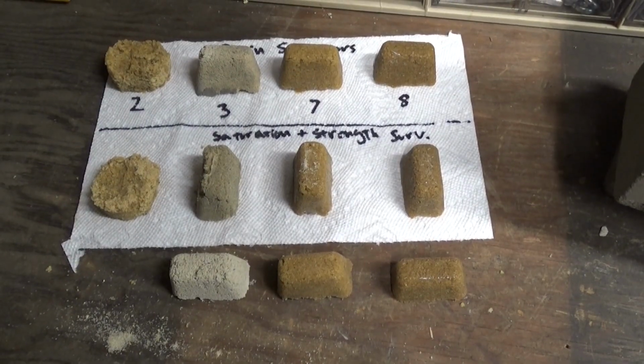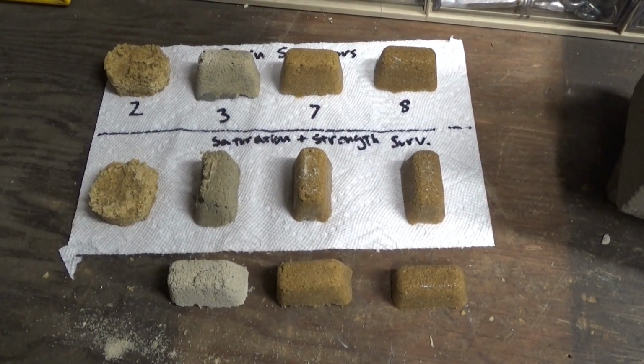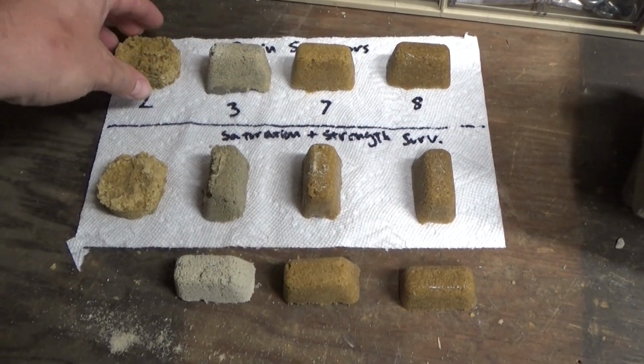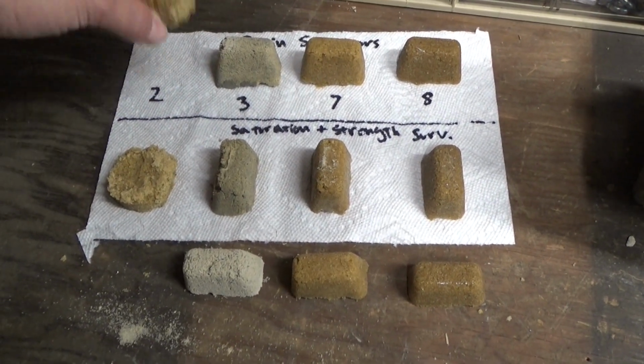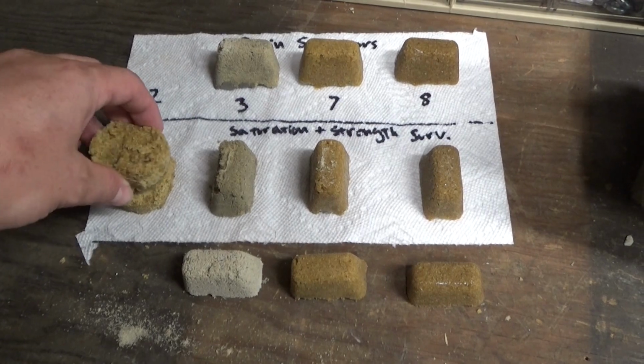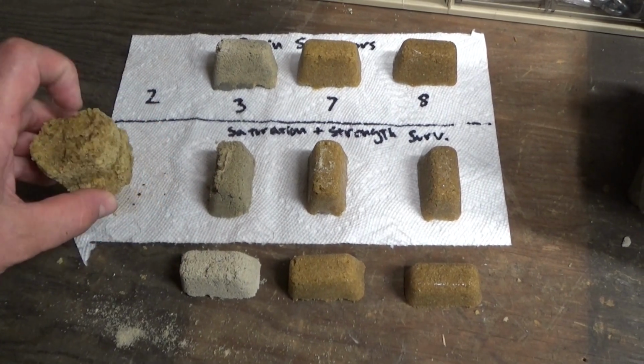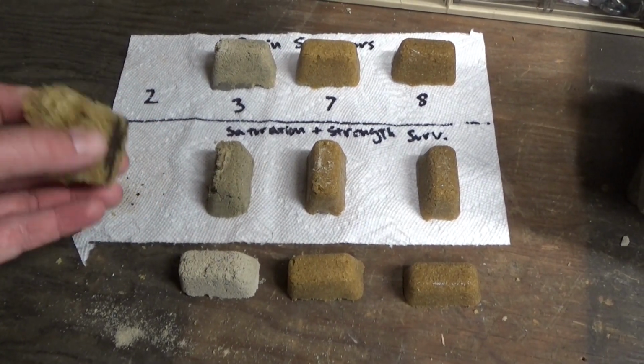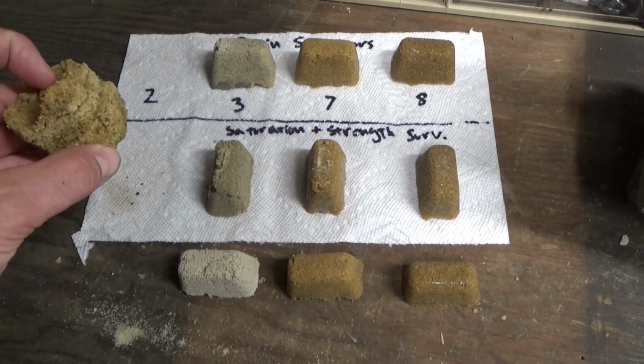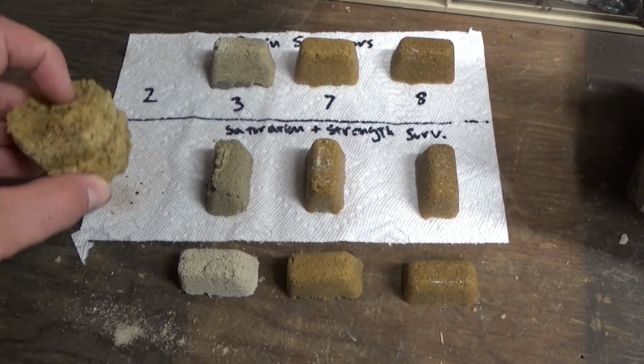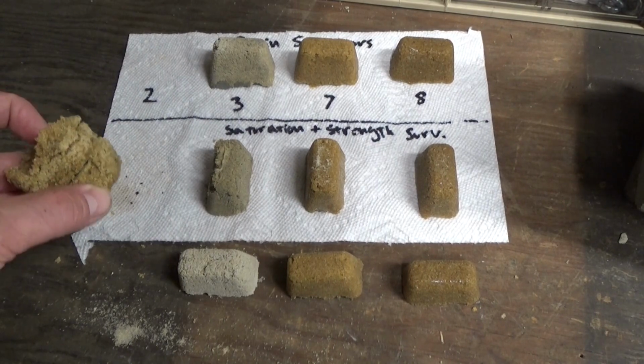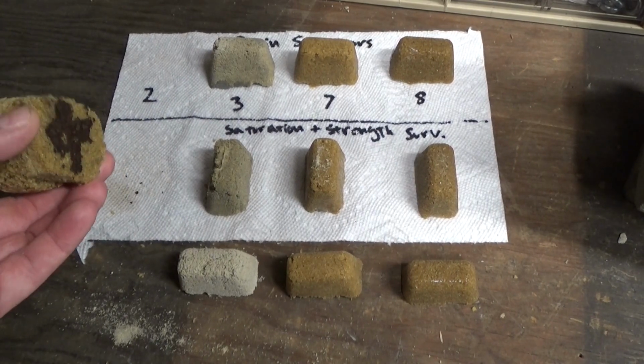So this is what we have for the most successful survivors so far. I'm going to eliminate number 2 because while it survived rain, saturation with water, and freezing, it did not survive thawing out again. It just crumbles in warm weather. That was the hot glue. I honestly didn't expect it to survive this well, but it did finally fail in the hot weather test.